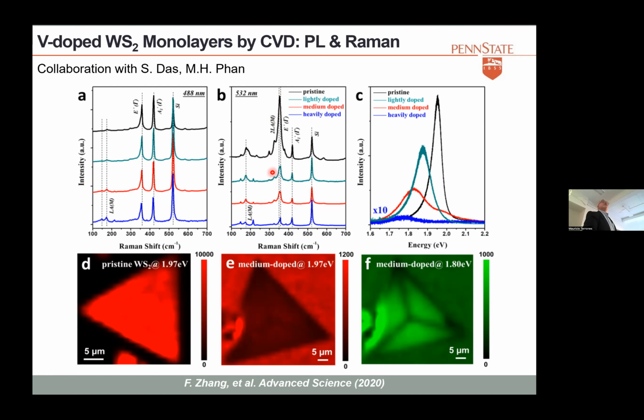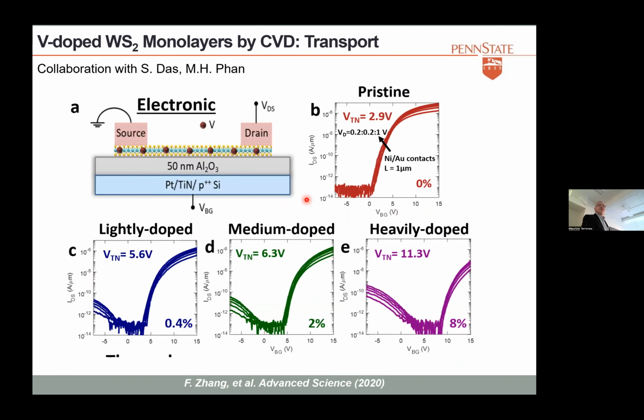But you can see as we introduce vanadium, with lightly doped, medium doped, heavily doped, this resonant peak decreases rapidly, and in the photoluminescence we also see that as we increase vanadium, we start seeing a shift towards the lower gap, right? So when we put vanadium, the gap is reducing, and that's something we're seeing. And of course, if you put too much vanadium, then the PL is also inhibited because you have many defects there. But you can see we are really seeing this in PL and even in Raman spectroscopy. So that means that the properties of the material have been changed.